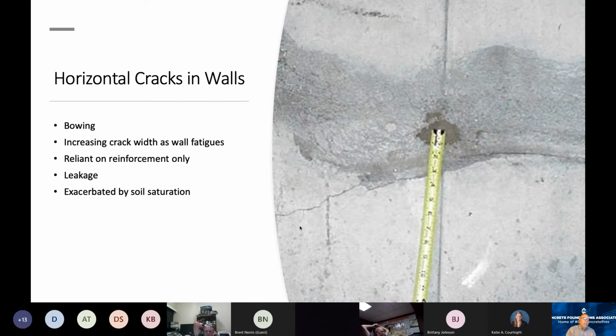Now, there's a difference between bowing and out of plane. Out of plane could have been created just by the wall being out of plumb when the contractor placed it. But we want to particularly look for bowing. We want to look for evidence of dimensional change, deformation, or displacement on each side of these cracks. Because once we get this crack in place, as you may know, we're relying fully on the reinforcement for structural performance. And steel's quite ductile. And once I start to get a horizontal crack with a load from the outside, and that pressure is a combination of soil and moisture, as well as maybe some applied loads at the grade level, the steel itself may not be sufficient to control the bending moment that's applied into that wall. And so we want to be very careful about the types of horizontal cracks that we're looking at.